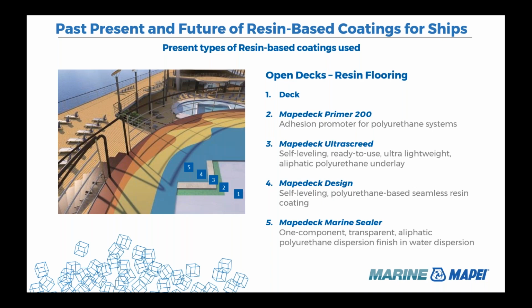a previous slide, the resin gives you the opportunity to create repetitive patterns or unique patterns on top of the surface. The resin top coat is not a paint. So you have to consider that everything that you see as a pattern or as a drawing is not painted, it is in full thickness. So we have at least, let's say, 3 to 5 millimeters of thickness of a top coat, typically. So whatever patterns you see on the top of the surface are not only on the top of it, but on the full thickness of the layer itself. Next slide.